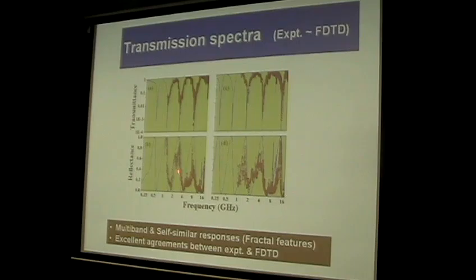We also found that this structure naturally possesses multi-band and self-similar response. You notice that the horizontal axis, the frequency, is on a log scale. The log scale means that if you have a periodic pattern, the structure is actually self-similar. You can understand this. And we performed the FDTD simulations. The simulation result is plotted as a blue line, and you can find the perfect agreement between experiment and simulations.